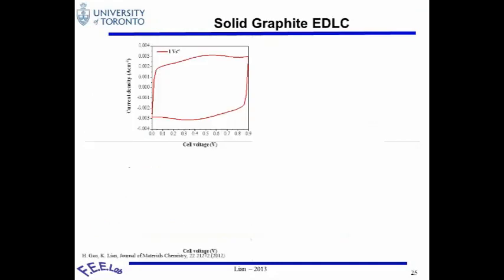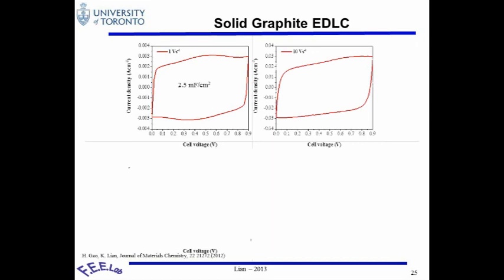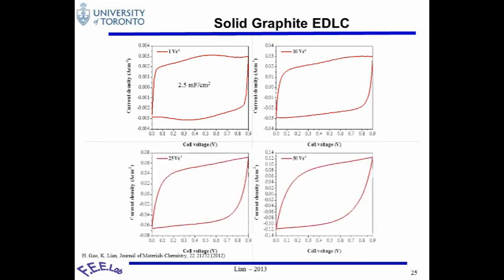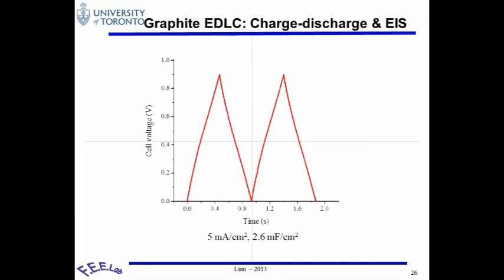Then we move on to look at the solid graphite EDLC capacitance. This is a very nice 1 volt per second, showing a nicely squared rectangular shape, 2.5 millifarads per centimeter square, at 10 volts, 25, and 50 volts. Up to 50 volts per second, we still can reach about 2.5 millifarad per centimeter square, which, as far as we know, is the highest capacity that can be achieved at this kind of rate. So we've looked at the charge-discharge.